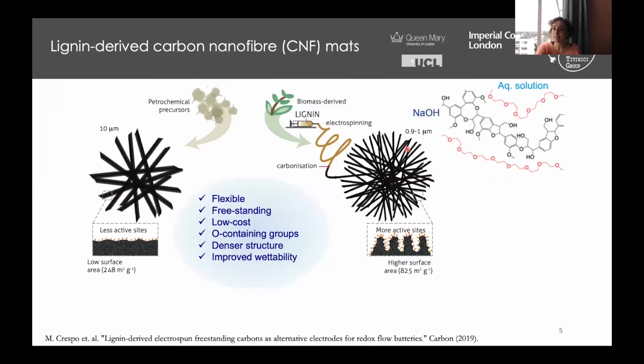So in this line, we have produced carbon fibers electrospun from lignin, also using PEO as a polymer to help the spinning of the solution. But most importantly, we've done that in water and using sodium hydroxide to obtain highly porous carbon fibers with more surface area and more active sites than normal carbon fibers that are produced from petrochemical precursors.